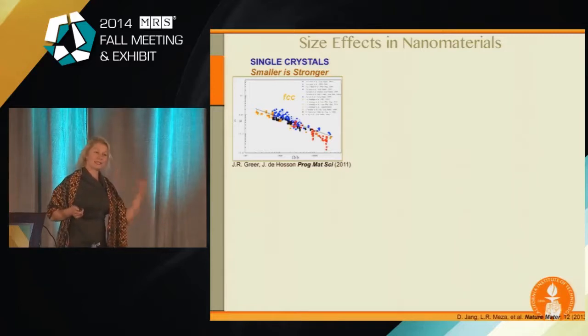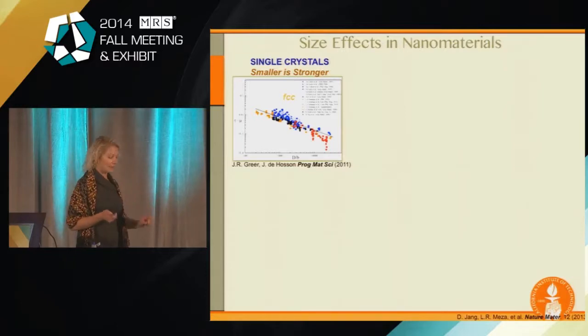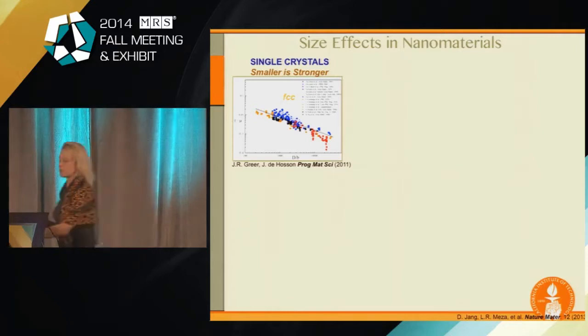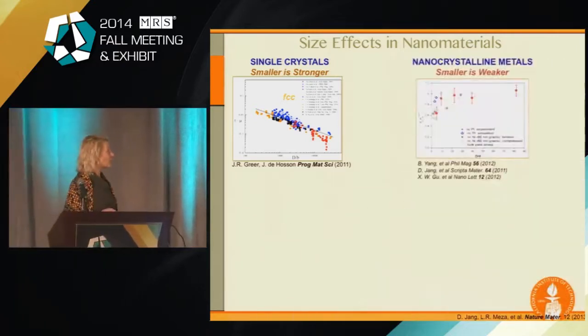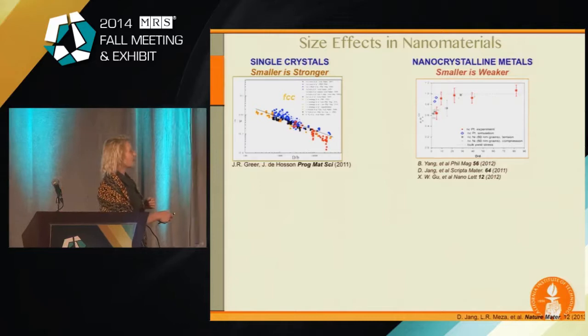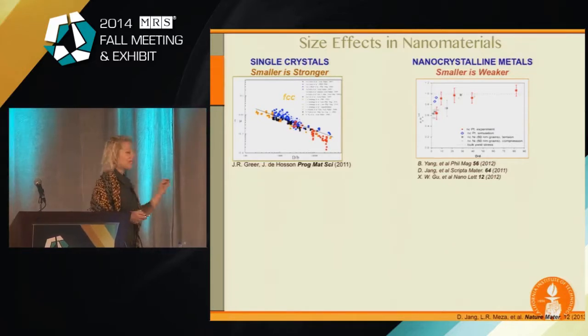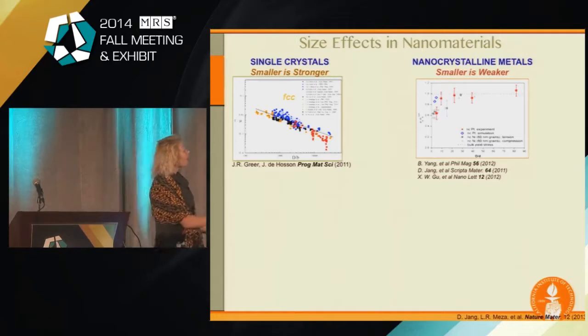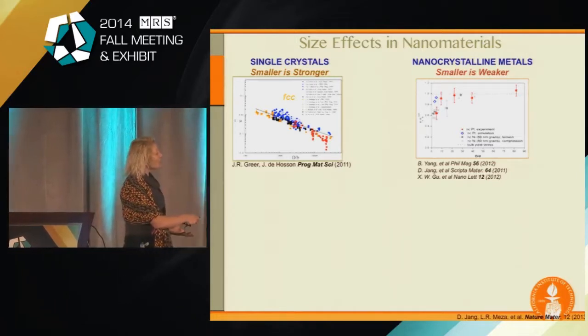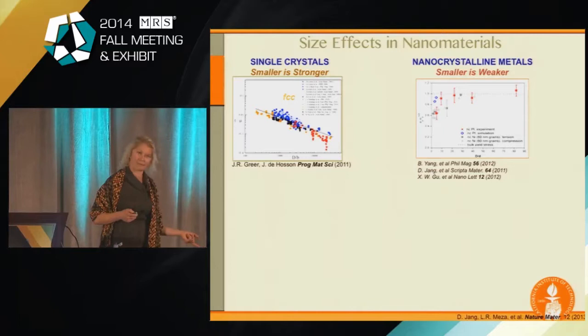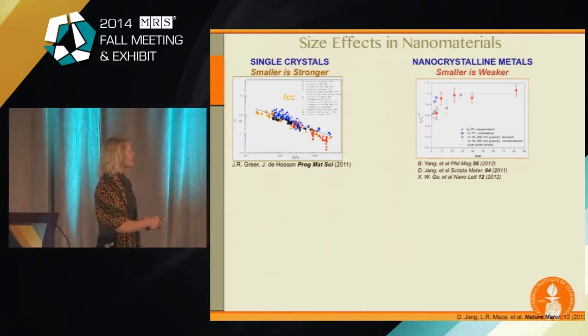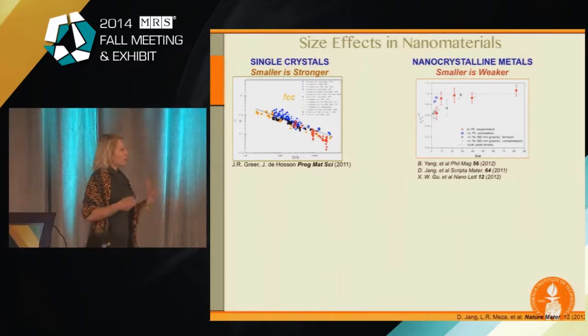Now take exactly the same metal and deposit it differently, by a different technique, and of course there are plenty of these techniques, such that there are now multiple grains in the structure. And all of a sudden, you see exactly the opposite effect. So when you populate the same metals, like the gold, the nickel, the copper that we were describing, all of a sudden you see the emergence of smaller is weaker. Now this is a more modest effect, it's not a log-log plot, but it's still something to be aware of. So sometimes materials can be stronger, sometimes they can be weaker.